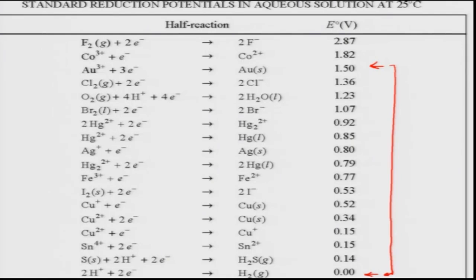Similarly, if I compare gold and silver, gold's standard reduction potential is 1.50 and silver's is 0.80. So, that means gold is highly noble as compared to silver. Now, if you have a gold silver alloy and dip it in acid medium, then gold will remain, silver would dissolve, and then we can have a porous gold structure, and that porosity could be in the nanometric range. That is what we call nanoporous material.